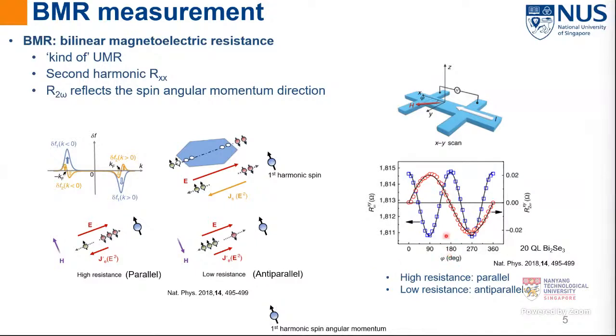Here is the published data with bismuth selenide in the XY scan. It can be seen that the second harmonic signal reaches the high resistance when the field rotates 90 degrees to the y-axis when the current is flowing along the x-axis. It means that for a positive x current, the spin is aligned in the positive y direction. This is the same as the published bismuth selenide spin texture and also the positive spin Hall angle case.